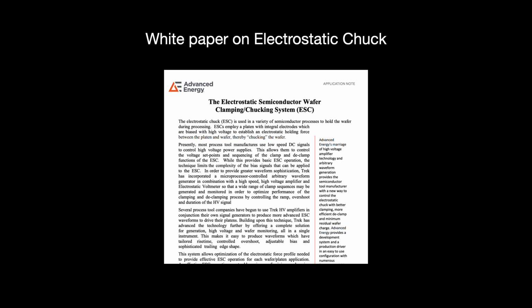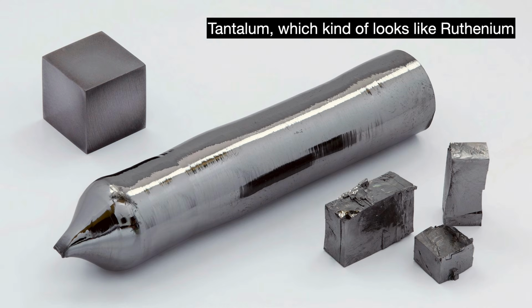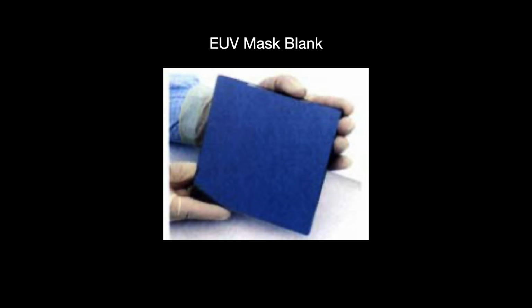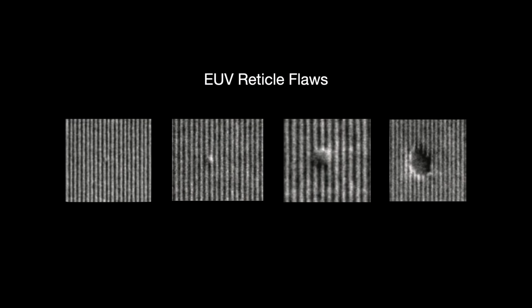Finally, in order to turn the mask blank into something useful, you have to pattern it. This is done by applying an absorber layer of tantalum on top of the capping layer, basically doing the same thing as the chromium patterning in DUV quartz glass masks. All of this is hard enough as it is, but wait, there is more. ASML asked Carl Zeiss that the mask blank should have only 0.003 defects per square centimeter. Considering the reticle is 142mm by 142mm large, that is basically 0 defects on the reticle. Zero defectivity is one of EUV lithography's key challenges to overcome.